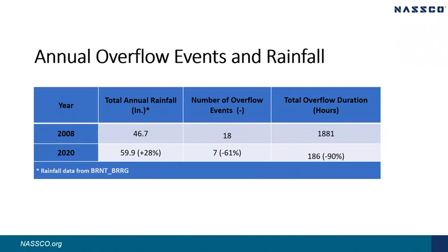Just another quick snapshot of our work and our results. Again, in 2008, when we began our rehab program, you can see there the annual rainfall in 2020 went from 46 to 59. So, an increase in annual rainfall of 28%. Number of overflow events went from 18 down to 7, a 61% decrease. And what's interesting, and again, these are just estimations, but it gives you a big picture idea. Our total overflow duration in hours went from about 1,800 hours there in 2008 when we started collecting that data down to 186 hours in 2020.